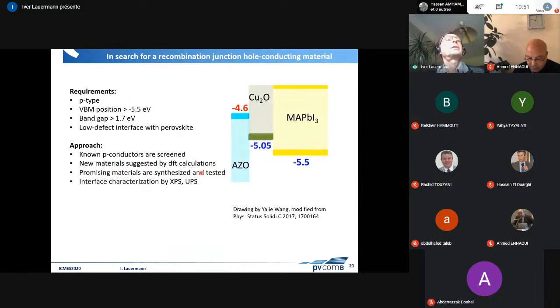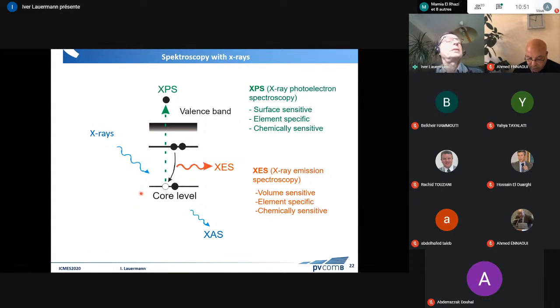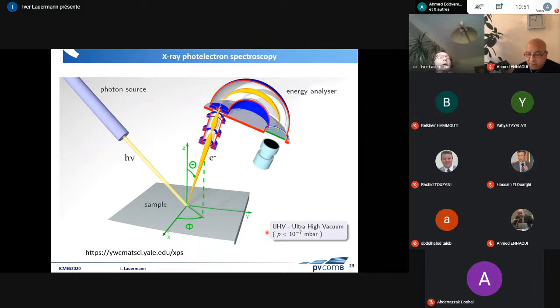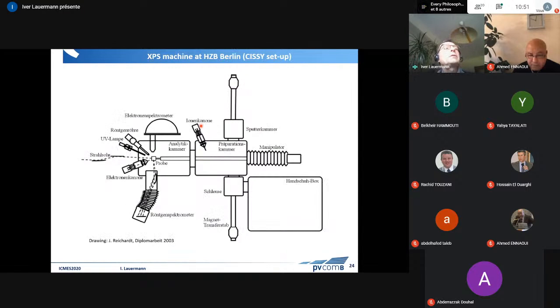And then we synthesize them and we test them, and we do our interface characterization using XPS, photoemission spectroscopy, and also X-ray absorption spectroscopy at the BESSY synchrotron. And of course, many of you are familiar with the principle of X-ray photoelectron spectroscopy. We irradiate the sample with X-rays. We look at the emitted electrons, and this is the machine that we use, where we can actually prepare samples in this part and then move them over to the analysis where we do XPS.